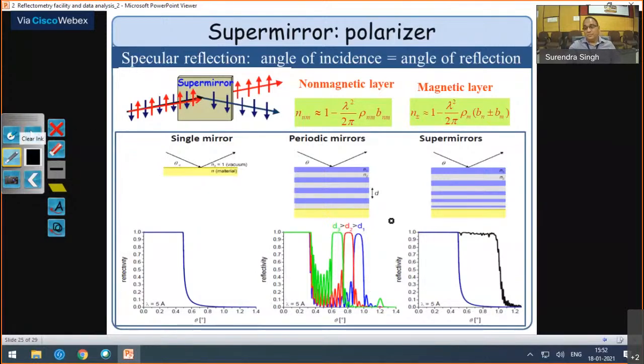Typically, if you choose this super mirror such that your minimum wavelength can give you polarization, then higher wavelengths will also work, because this theta depends on the wavelength and on what we call m. This super mirror is also used for the time-of-flight method, where we use different wavelengths at some particular angle of incidence — it doesn't matter, because all wavelengths will be reflected from the super mirror.